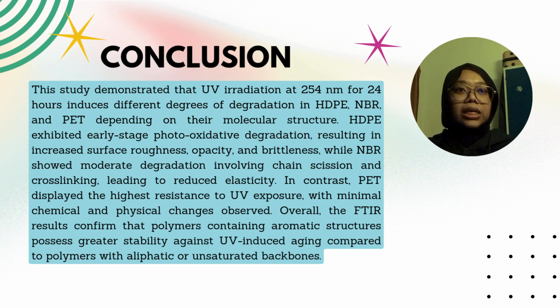HDPE exhibited early stage photooxidative degradation resulting in increased surface roughness, opacity, and brittleness, while NBR showed moderate degradation involving chain scission and cross-linking, leading to reduced elasticity. In contrast, PET displayed the highest resistance to UV exposure, with minimal chemical and physical changes observed.